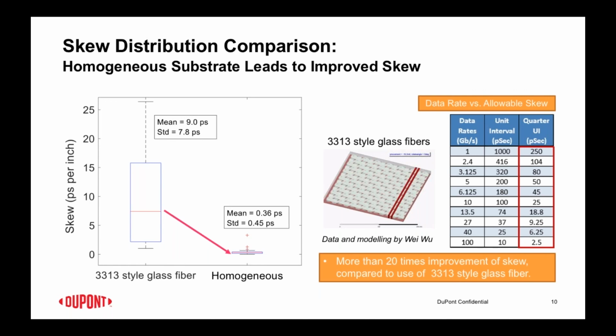What this is showing is that a quarter of a unit interval, which is the part where there's a significant impact on signal integrity for a differential pair, starts being a real possibility as we're getting into data rates above 50 gigabits per second. So we're into that kind of data rate. If you look at the graph on the left, style 3313 is showing a mean value for skew of about 9 picoseconds, whereas a homogeneous material like the Pyralux laminates is showing a mean value for skew under half a picosecond. So better than a 10x improvement.